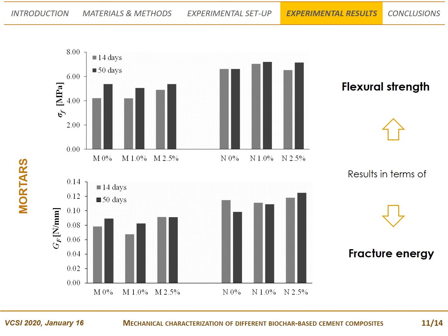The obtained results could suggest to consider for future research different percentages, and in particular higher, of biochar. However, it is worth noticing that 2.5% was chosen as maximum percentage in this work, since higher biochar additions involve a considerable increase of water or superplasticizer in order to obtain good flowability.